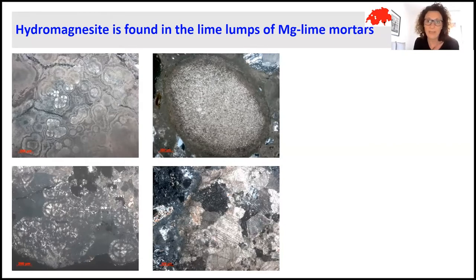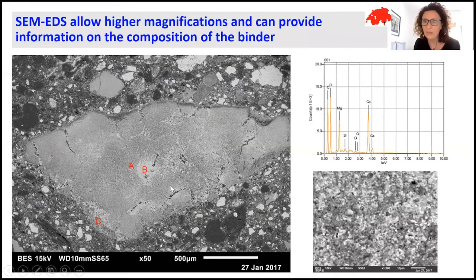This is the case for the binder, which has very microcrystalline components. So in this case, I can use, for example, higher magnification by means of a scanning electron microscope, in which I can have much higher magnification, and I can also obtain the chemical analysis directly in the lime lumps. As I see here in the spectrum, there is the presence of both calcium and magnesium, and I can also have a sort of quantification of the relative proportion of these two elements.